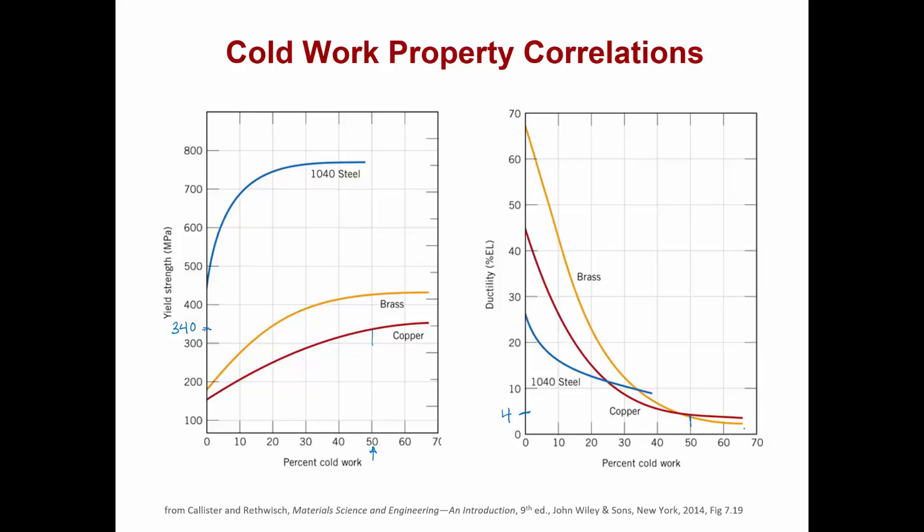That's because long before we'd reached 75 percent cold work, the sample will have lost so much ductility and become so brittle that the sample fractured. In fact, it's impossible to cold work this sample to 75 percent.